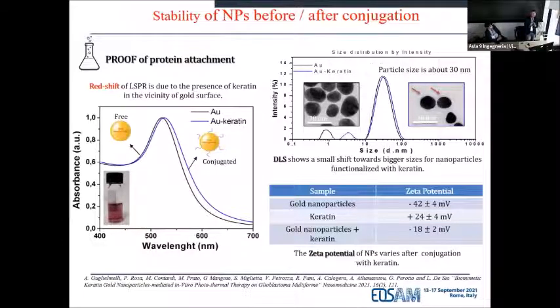And I want to give you just an insight into this capability to make keratin-coated golden nanoparticles. First off, you can see the difference in terms of spectral response. Once you connect the keratin here, there is this shift of the plasmon band, highlighting that there is a local change in the refractive index, because now we go from citrate, like the pristine particles we have, to particles coated with keratin. Since we change locally the refractive index, there is this shift. Moreover, you can see this very tiny organic layer surrounding the nanoparticles, confirming the presence of keratin. And lastly, of course, there is a strong change in the zeta potential.